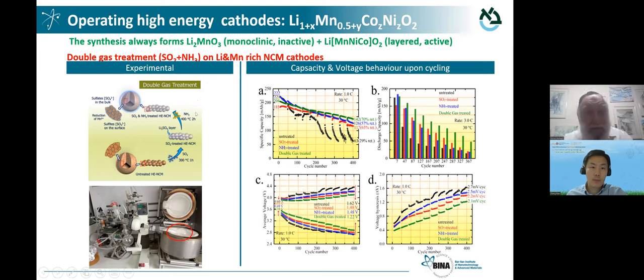Here, thanks to the structure, thanks to the formation of this phase, what adds capacity is oxygen. We have oxygen redox. I believe that this was dealt in this meeting before with works and talks about this type of materials. So when the oxygens become active, they are very reactive. And then the key issue is to isolate the active mass and the electrolyte solution. When we have oxygen redox activity, we have also oxygen evolution. We form very reactive peroxide, peroxo, and superoxo species that react readily with the electrolyte solution. And thereby, the key issue is to form buffer zones.